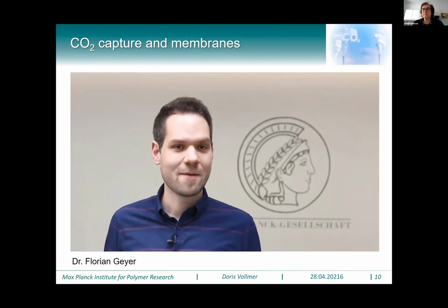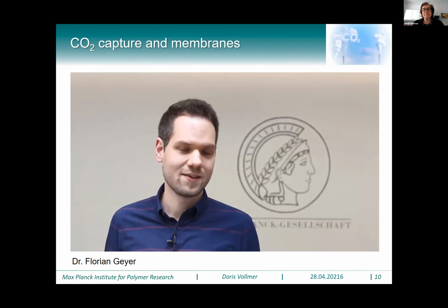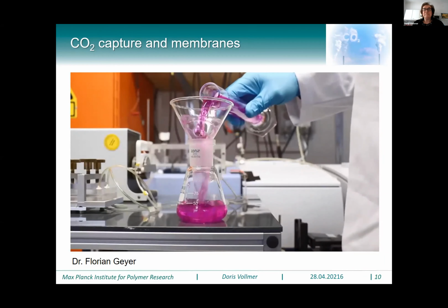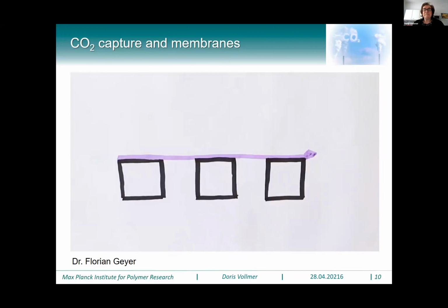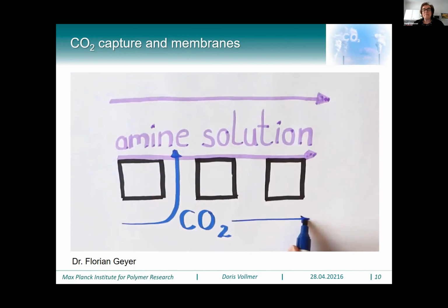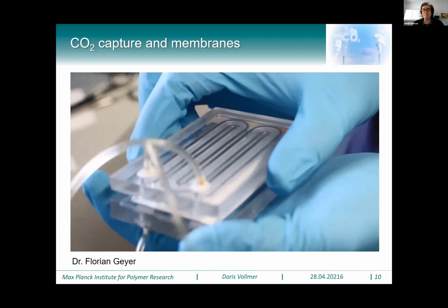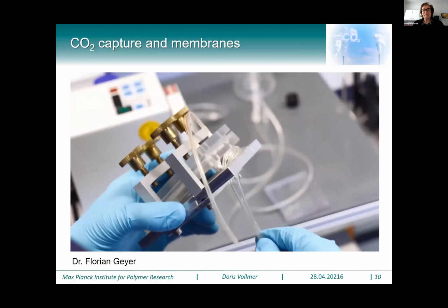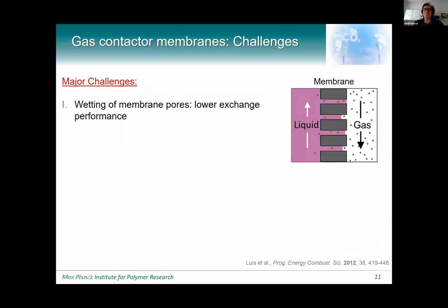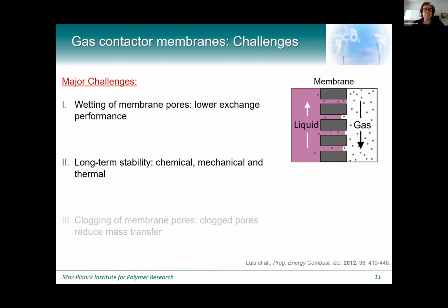One strategy to capture carbon dioxide is to make use of gas exchange membranes. Here, an amine solution flows over a porous membrane. This solution can bind carbon dioxide. The CO2-containing waste gas streams across the other side of the membrane. Most importantly, gas can diffuse through it. However, we have some problems. Amine solution easily wets the membrane. This greatly reduces the contact area between the amine solution and the carbon dioxide containing gas. Furthermore, amine solutions are quite aggressive because they have a huge pH. Therefore, they can destroy the membrane, and we can have clogging of the membrane, also reducing mass transfer.